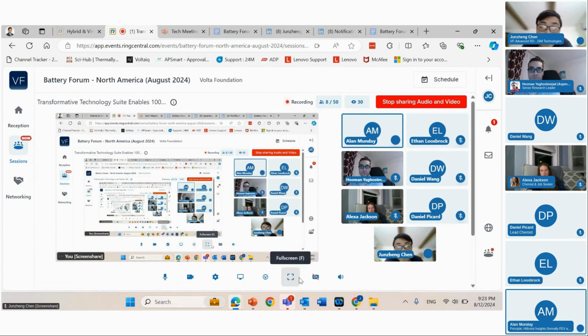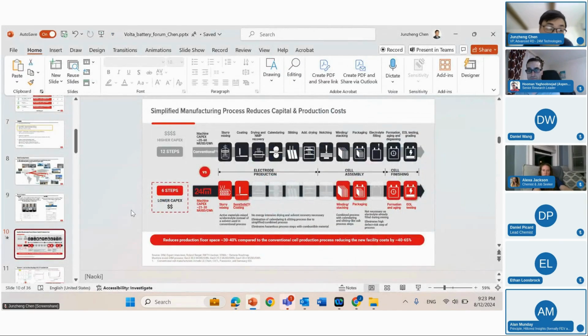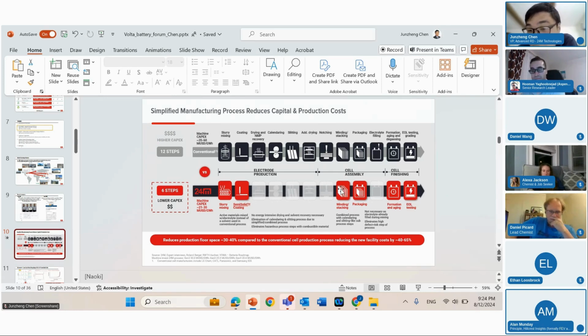Going back to the previous question about the throughput of your new process, the throughput is driven by the takt time rather than the number of steps. Does your process increase the takt time for your thicker coating that you mentioned? Yeah. First, the mixing step is direct. So our current limiting factor is not coating, it's not the slurry mixing step. Our main limiting factor for this electrode is the stacking and winding step.